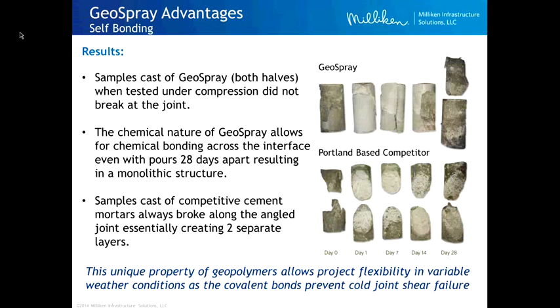The cylinders on the bottom are Portland cement cylinders that were poured on a 45-degree angle, and then at different intervals. You can see day 1 through day 28. They came back in and poured on it, let it cure. If we broke those cylinders, provided or put them under a compressive load, they would always break along the cold joint, and that's what we're seeing here. With our material, as it rebonds with itself, we do not get a cold joint, and so you can see up here, you can see where that line was in some of these. It just broke wherever the shear failure was within that cylinder.